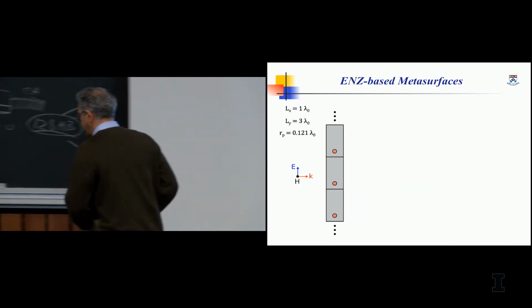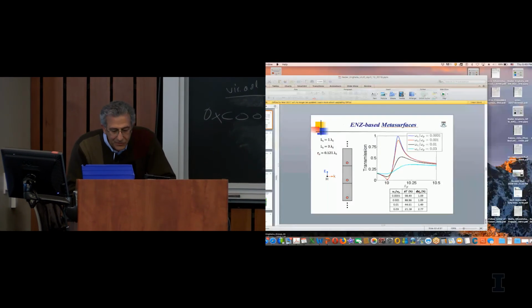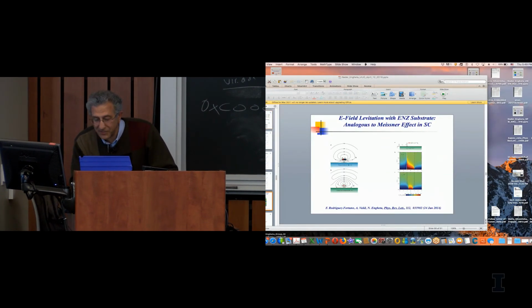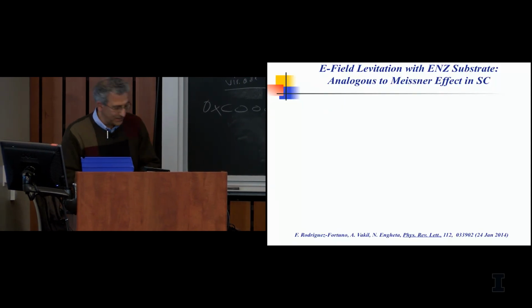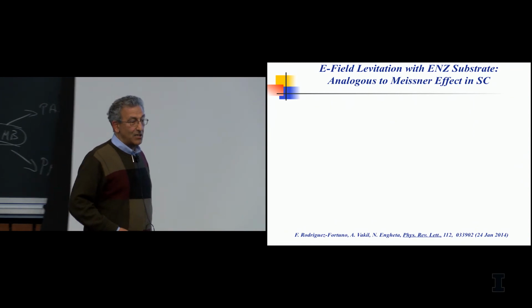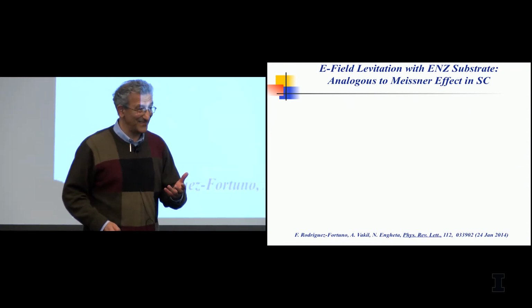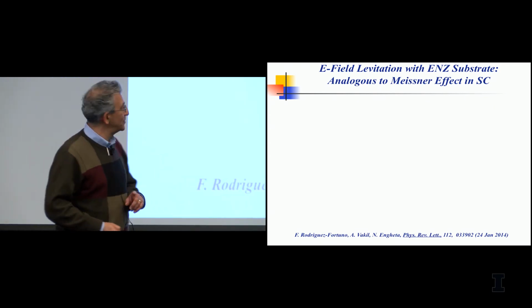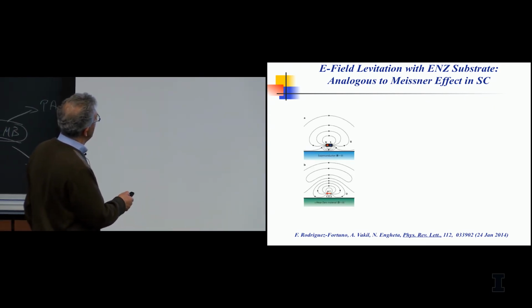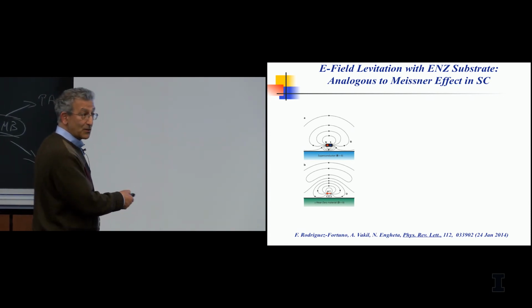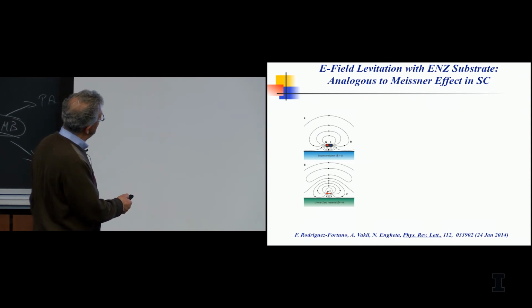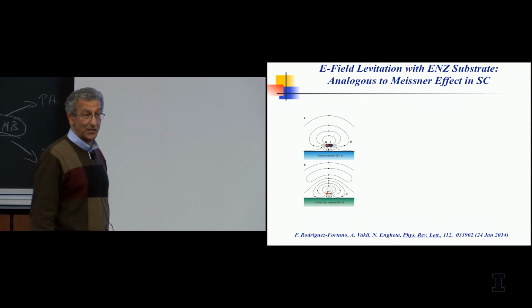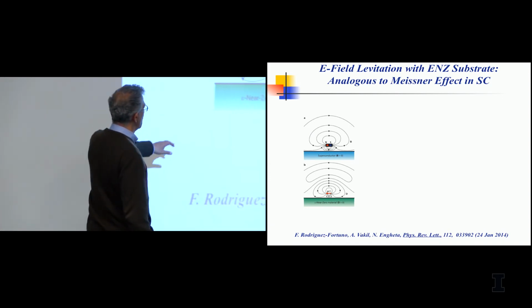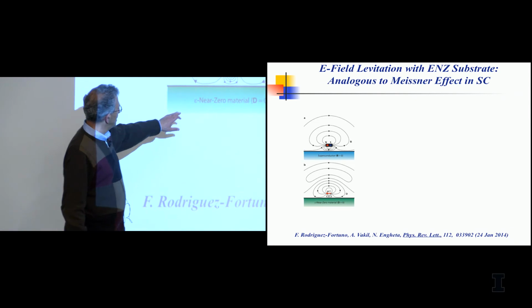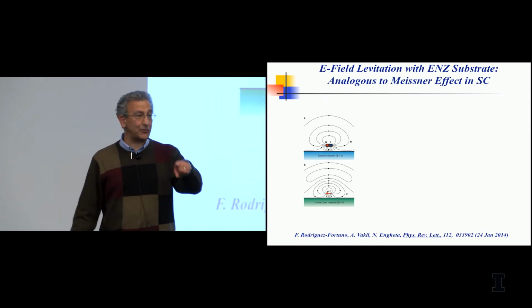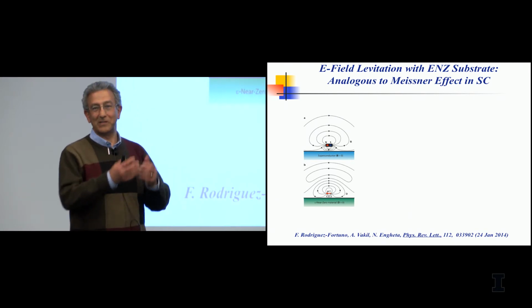Now, let me jump over, I know there's no time. One of the interesting features is that we found an interesting analogy between the Meissner effect in superconductivity and this structure for epsilon near zero. Now, you all know that the Meissner effect would cause a magnet to suspend or levitate over a perfect conductor. And the reason for that is the magnetic induction B cannot go into the superconductor. Now, for the case of ENZ, it's the dual of that, but from a classical point of view. So vector D has to be equal to 0.